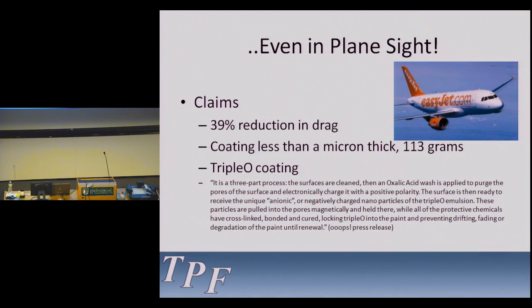This one just came up last month. Airplanes. EasyJet in the UK has adopted this new coating called TripleO, which they claim is a 39% reduction in drag. It's a spray-on coating about a micron thick, and there's about 113 grams of nanomaterial per plane. I guess this is probably either a silica or aluminum material, and they're using it to fill the microscopic cracks in the aluminum. Now, the 39% reduction in drag is a way oversimplification because there's different kinds of drag on an airplane. There's parasitic drag, there's surface drag, there's lift-induced drag, etc.